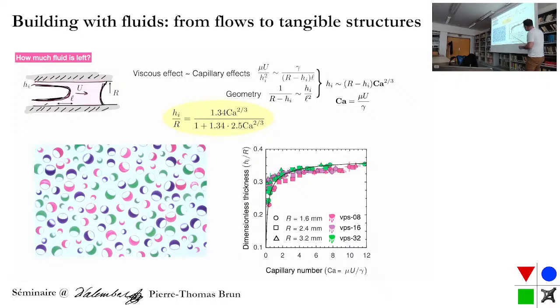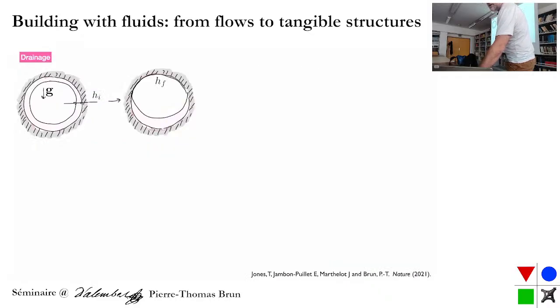Yeah, that's sort of important. So if you push fast enough, essentially whatever was a 2/3 is more or less something that's flat. And so essentially, as long as you push fast enough, you get basically 30% of your radius as your initial thickness. So that's the initial condition of our problem.